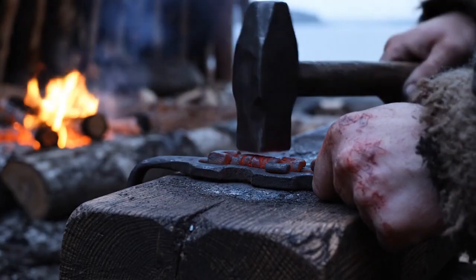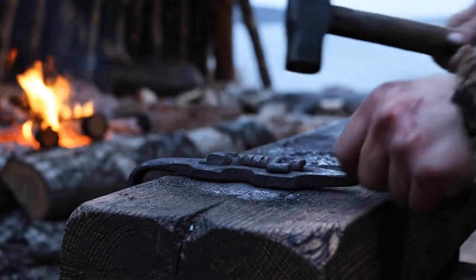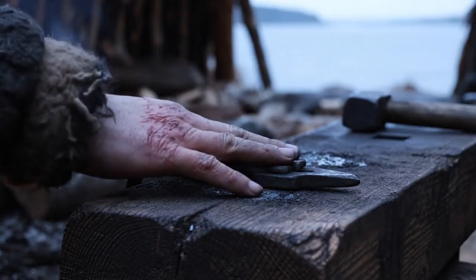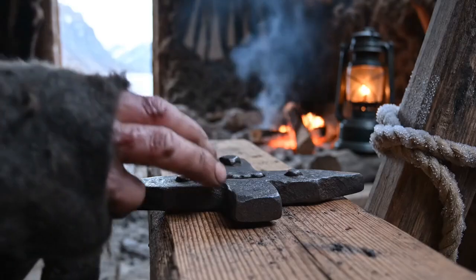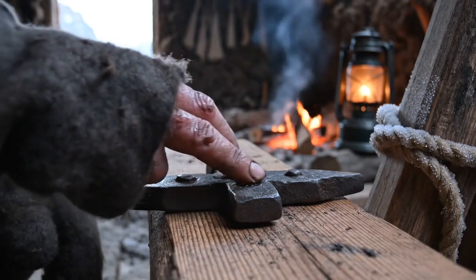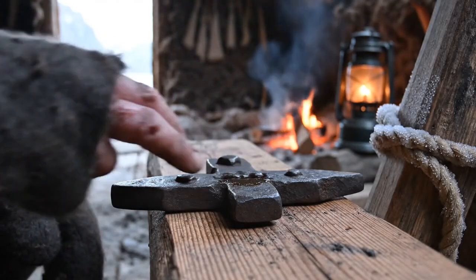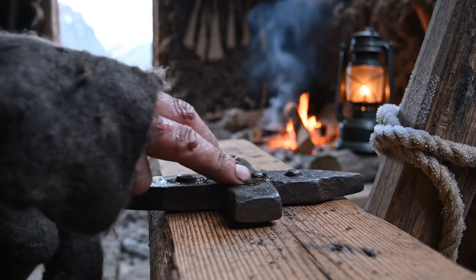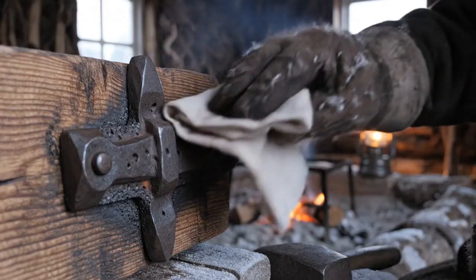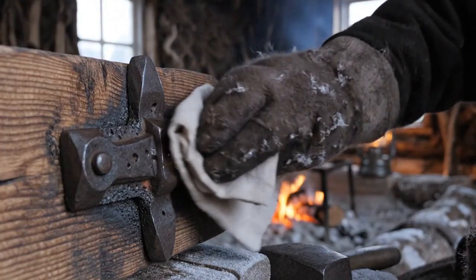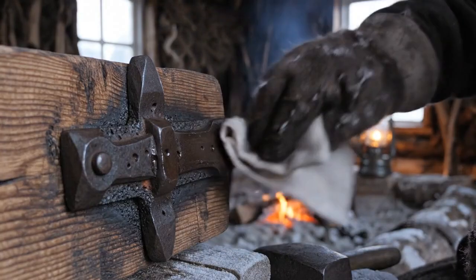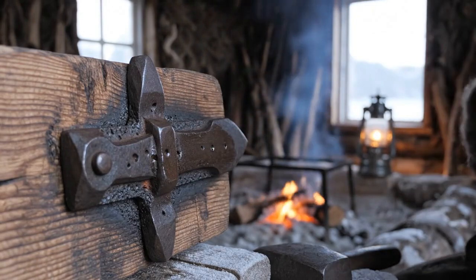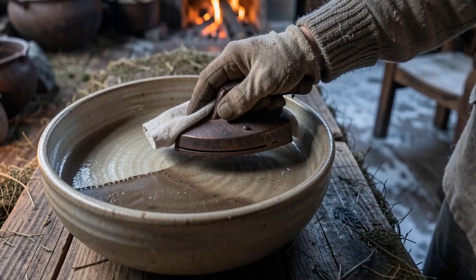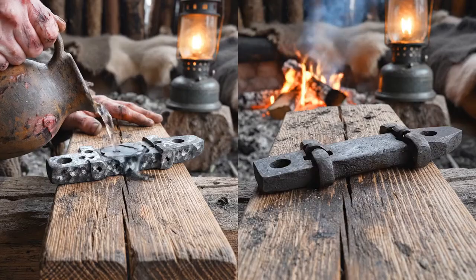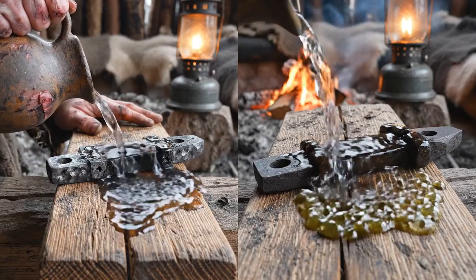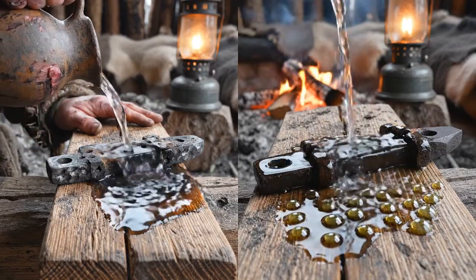Now, the next step is the one most people skip. It is also the step that separated a Norse smith whose blade survived 20 years at sea from one whose tools pitted through in 2 winters. Stay with this. Let the first layer sit for about 30 seconds while the piece is still hot enough to keep reacting. The surface will darken, then apply a second thin wipe. Same lightness. Let it smoke again. Wait another 30 seconds. Apply a third and final thin wipe. 3 layers total, all thin, all on a hot surface, each one building on the one before it.